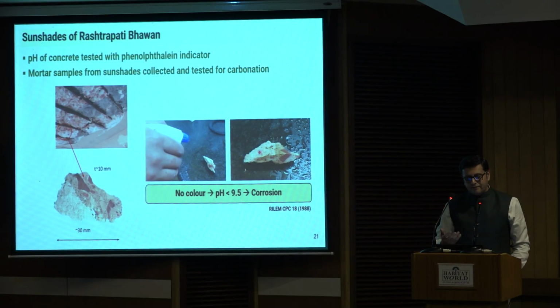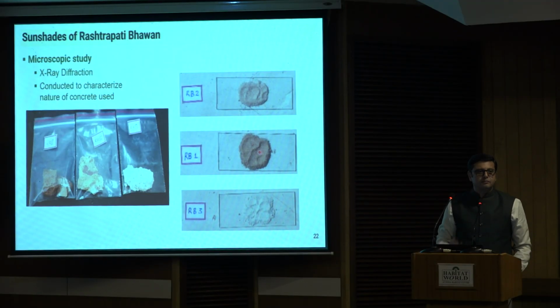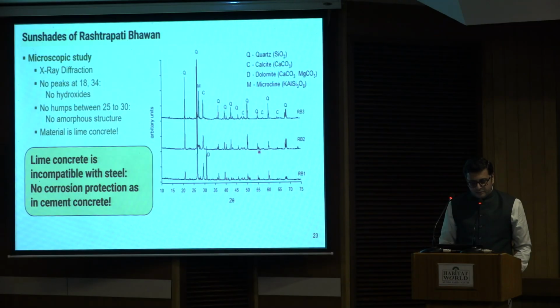And it started becoming evident that it was really lime that was used for concrete and not cement. So multiple tests that we conducted, from visual to all the other tests, confirmed that we were looking at lime concrete and not cement concrete.